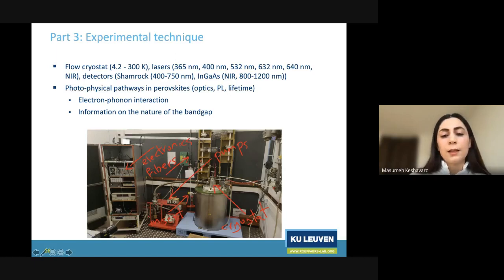For that, this is again a magnet, but inside is a cryostat. In the cryostat, there is an insert. The insert is coupled to a fiber. The fiber has two parts, two lines, one line in the middle, through which we are exciting the sample with a laser. And there are a lot of other fibers, like 11 smaller fibers around the excitation path, through which we collect the photoluminescence light coming from the sample. And the detection path is on the other side of the image. You cannot see it. And these are the electronics controlling the setup. So through these kinds of measurements, one can access the photophysical pathways in perovskites with a combination of optics, steady-state, and transient photoluminescence measurements. Then one can access the electron-phonon interactions and information on the nature of the band gap in the material.